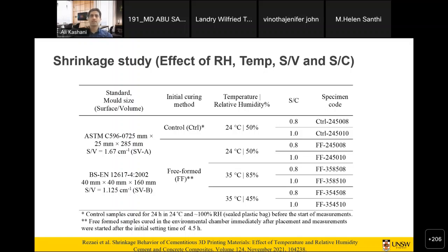We also looked at the sand to cement ratio. A higher amount of aggregates can limit the amount of shrinkage. So we looked at how we can increase the amount of sand while the material can still be printable, and how it would affect the drying shrinkage.